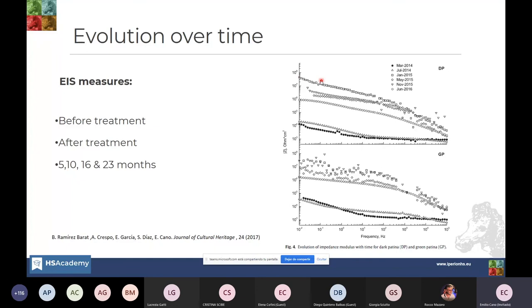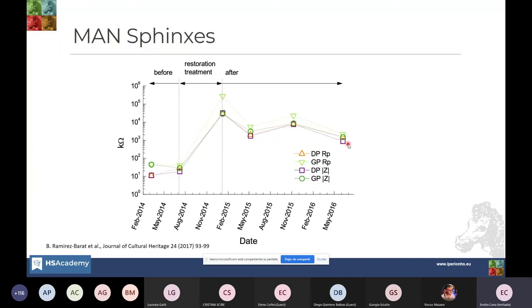and it is the maximum impedance we get. But repeating after 5, 10, 16, and 23 months, we have seen how the performance of this coating is decreasing. So if we plot this against time, we can see very clearly how this is decreasing, and we can anticipate that it will fail in about 4-5 years.